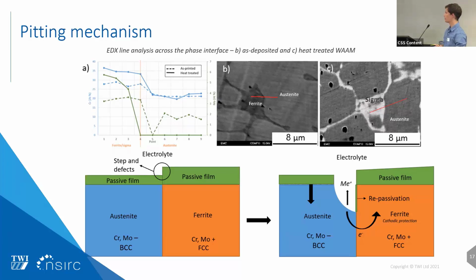That causes the austenite to dissolve preferentially, since it is depleted in molybdenum at that location due to the nearby phase. Molybdenum is well known to improve the pitting resistance of 316 alloys, especially in chloride-rich environments, because it slows the active dissolution of the matrix. Since we have a depletion at that point, we have a higher dissolution rate, and we are much more likely to form a pit because of it.